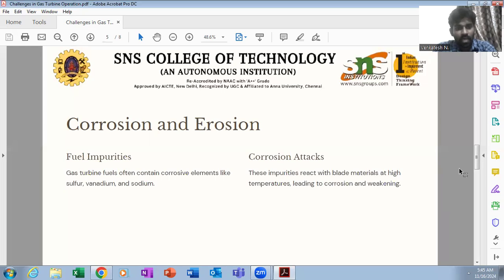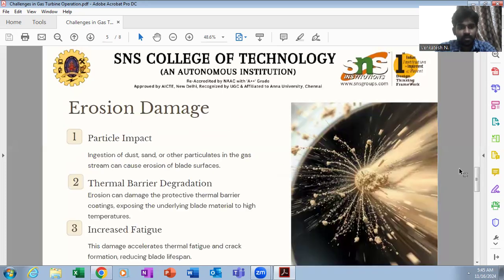Then corrosion and erosion. Fuel impurities: gas turbine fuels often contain corrosive elements like sulfur, vanadium, and sodium. Corrosion attacks: these impurities react with blade materials at high temperatures, leading to corrosion and weakening. And erosion damage. Particle impact: ingestion of dust, sand, or other particulates in the gas stream can cause erosion of blade surfaces. Thermal barrier degradation: erosion can damage the protective thermal barrier coatings, exposing the underlying blade material to high temperatures. Increased fatigue: this damage accelerates thermal fatigue and crack formation, reducing blade lifespan.